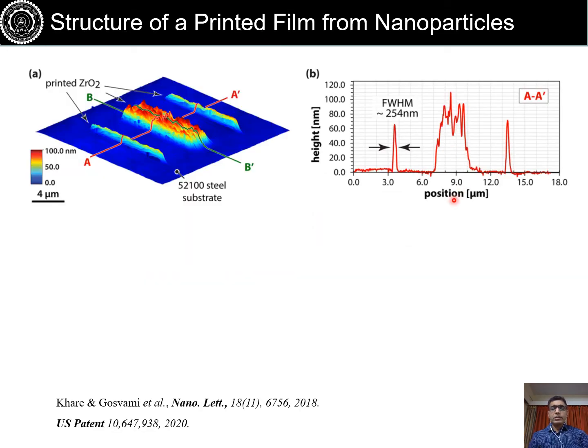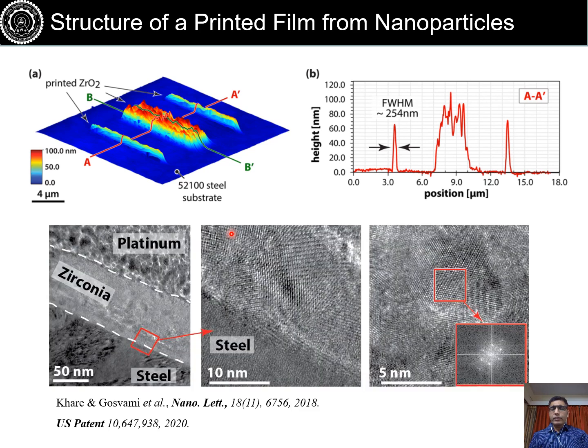This work was done in collaboration with Pixeligent, using zirconia nanoparticle. Here we see that we wrote line pattern, we drew rectangular pattern, and then characterized these patterns, and we found that these patterns are extremely robust. This was 5 nanometer zirconia nanoparticle, and after doing this sliding test, we see that these particles have completely sintered together, and there is a very sharp interface between the substrate, which is steel, and this zirconia film, which is deposited by sliding AFM probe, and these nanoparticles have fused together. And in the chemical characterization, we could not even find the capping agent which is used for dispersion of these particles, so they have sheared off due to this high stress conditions.